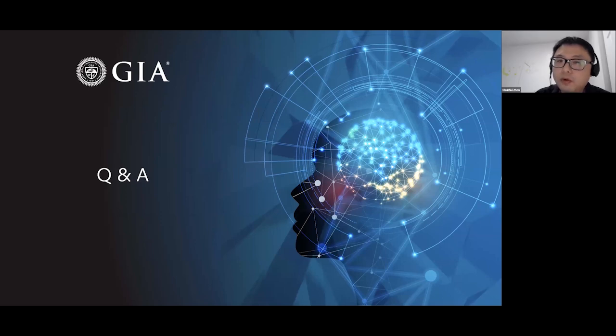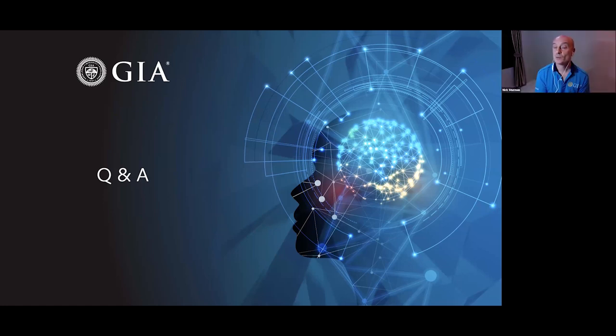Okay, thank you. So why do some of the pearls show such a large space between the bead and the pearl, like a gap? This is just during the formation. Maybe the epithelial cells that were put in the mantle with the bead didn't form correctly, and it produced a pocket of organic matter rather than creating a nice smooth coating of nacre around the bead.